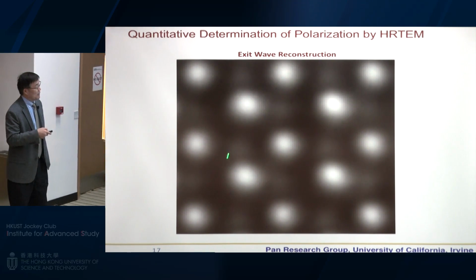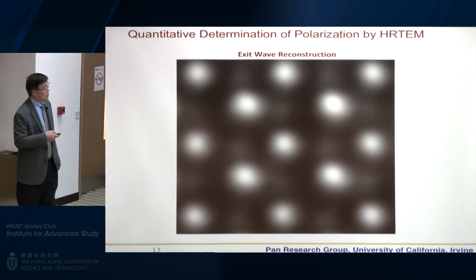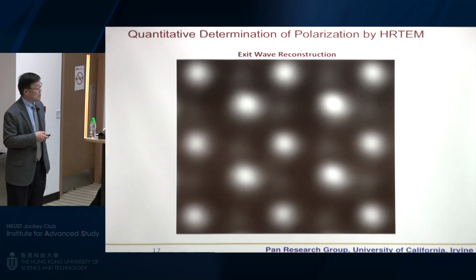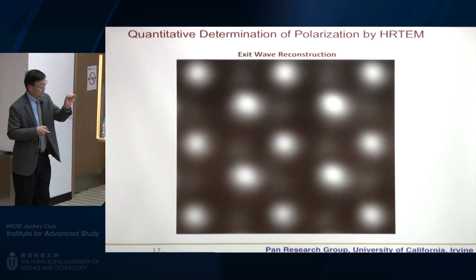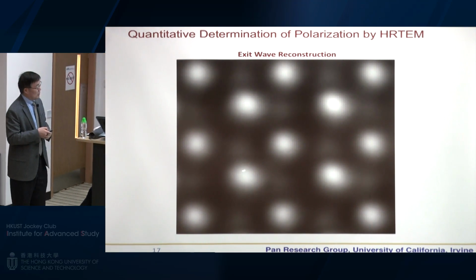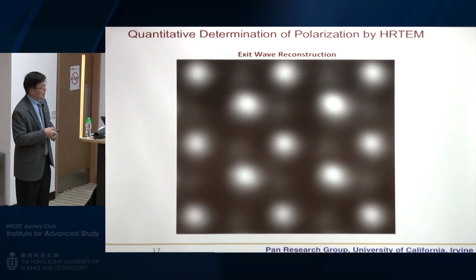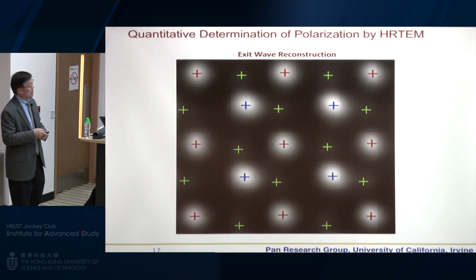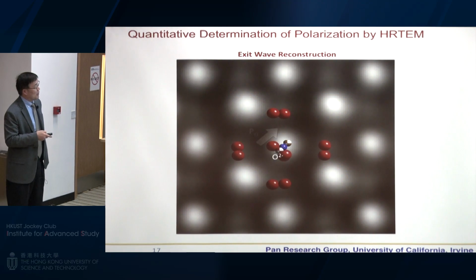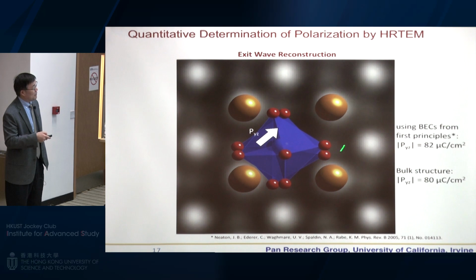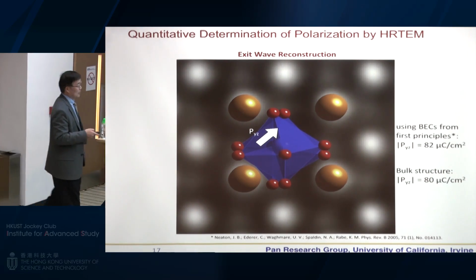And we developed two quite important methods. One is using atomic resolution TEM to determine the spatial distribution of the dipole moment. In other words, we can map the polarization in the ferroelectric material from unit cell to unit cell. So what we do is determine the positions of different kinds of cations. This is bismuth in bismuth ferrite, iron, and that is oxygen. After getting all these positions, you can calculate the dipole moment of this unit cell. Actually, that is very close to the value in a single crystal.